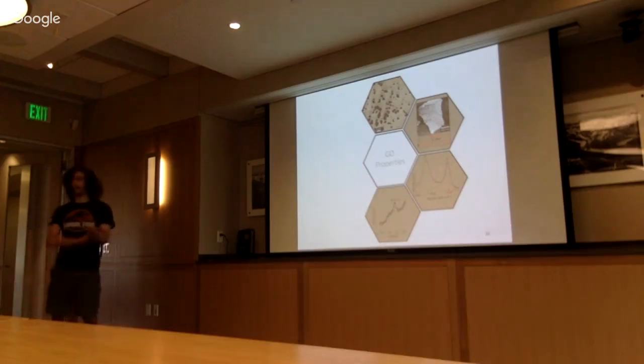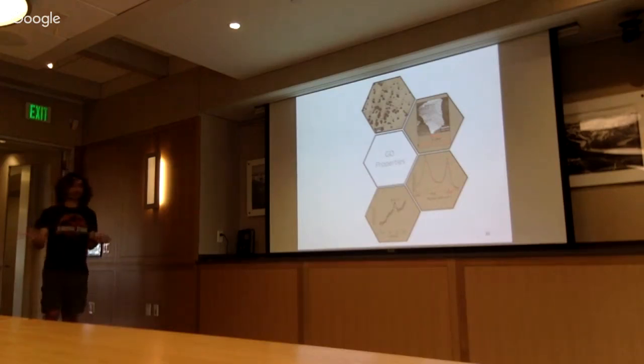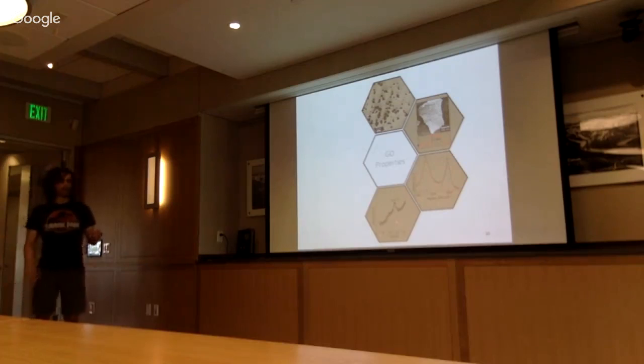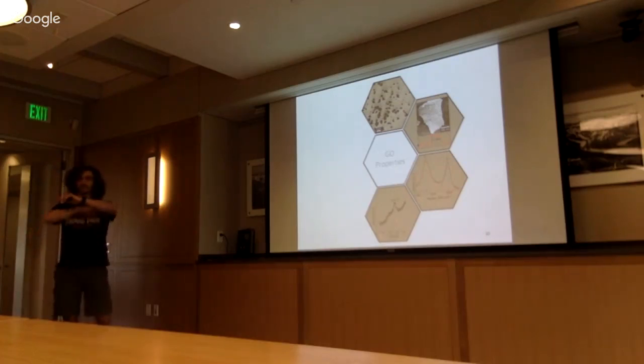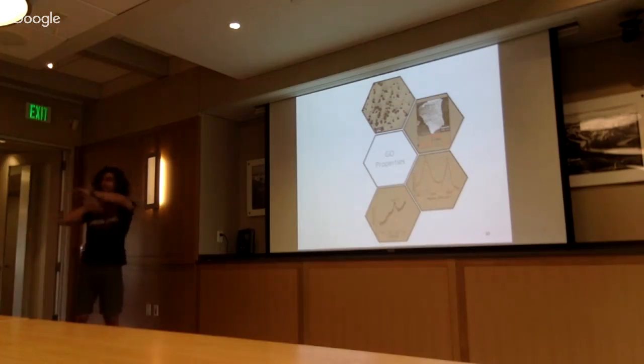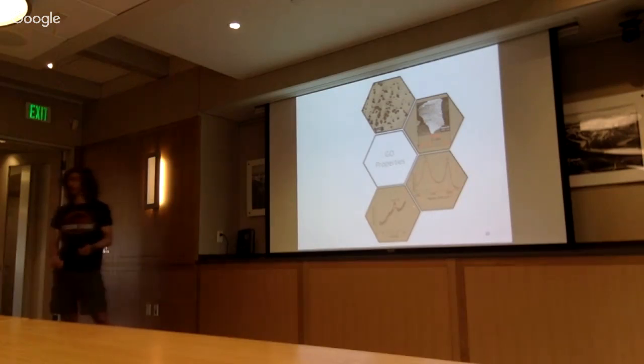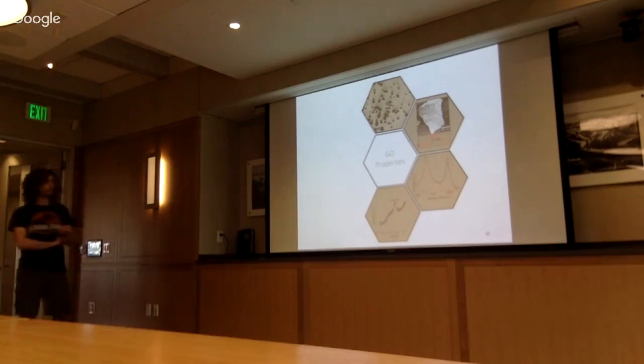And we have X-ray diffraction, from now on just XRD. And basically XRD is really important because it tells us how these layers are stacked and the separation distance between the layers. And the separation distance is about 8 angstrom, so less than a nanometer.